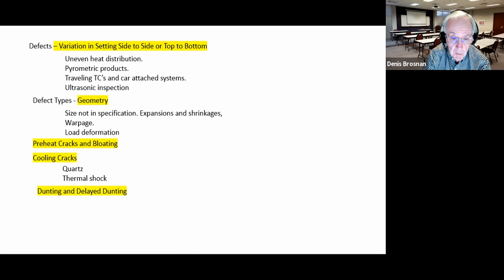Cooling cracks. Cooling cracks mainly due to quartz in many of the traditional industries. That's on cooling from the kiln soak temperature down to the temperature at which quartz inverts, 573 degrees C. So many of the cooling schedules with those products that contain quartz are designed to cool very quickly down to where quartz inverts from beta to alpha and cool very slowly through that transition. That's called the quick cool. I showed you a graph of a quick cool earlier in the course.